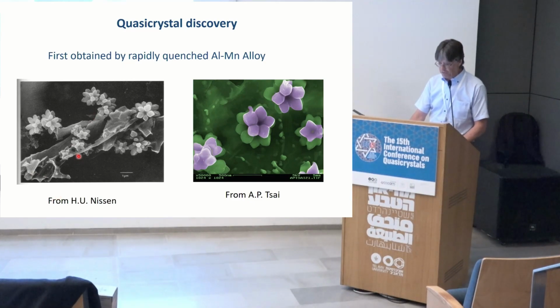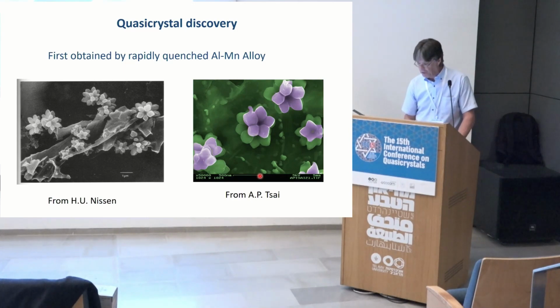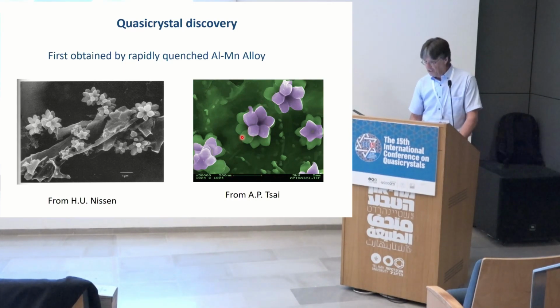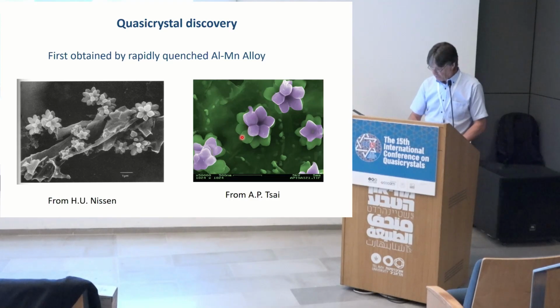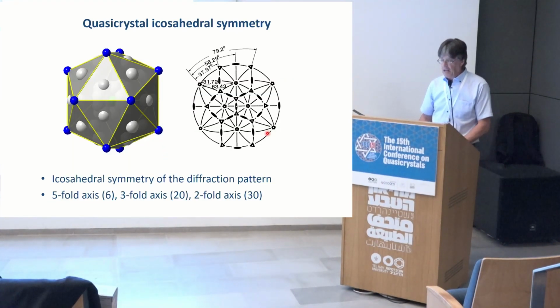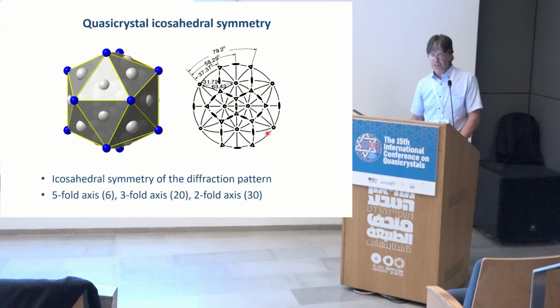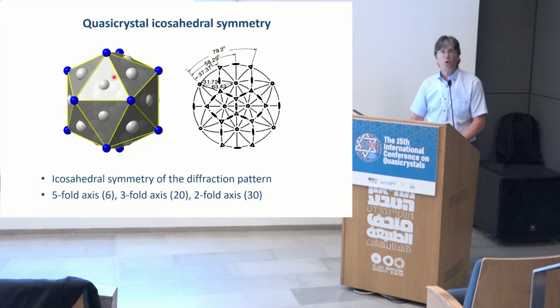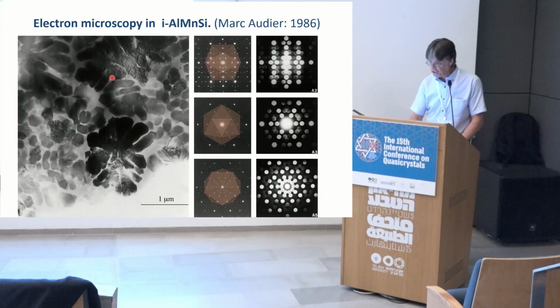So that's a nice view from Professor Nissen, and another one from An-Pang Tsai, where you see the nice aluminium manganese rapidly quenched alloy with the pentagonal flowers. And those quasicrystals, they have icosahedral symmetry. Icosahedral symmetry is characterized by a fivefold axis here, threefold axis here and a twofold axis. And of course, you have a relationship between all those angles. And this must be fulfilled if you look at your diffraction pattern.